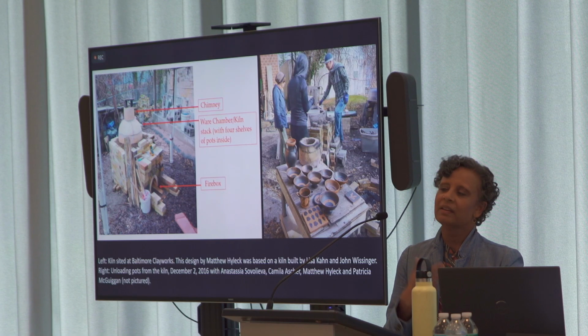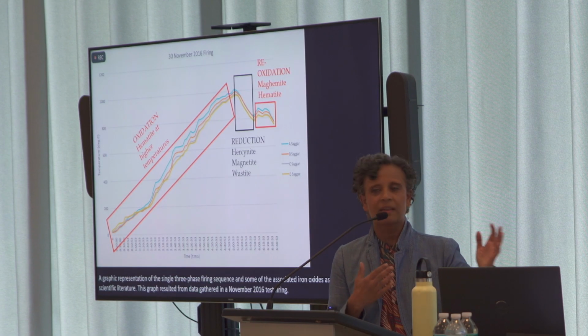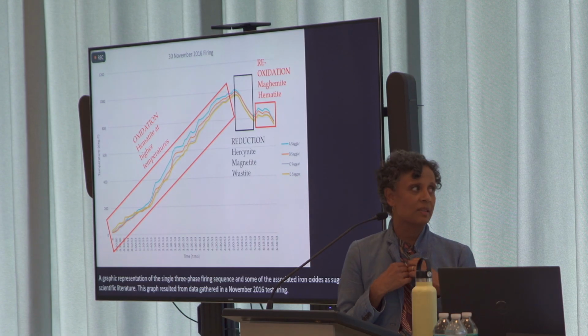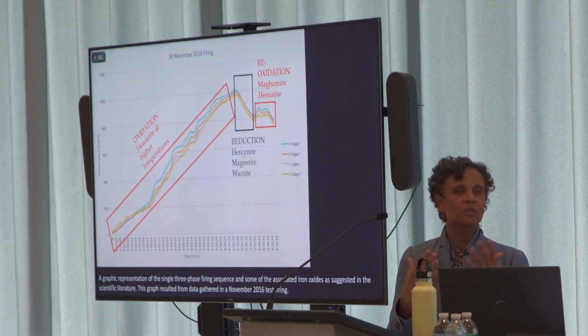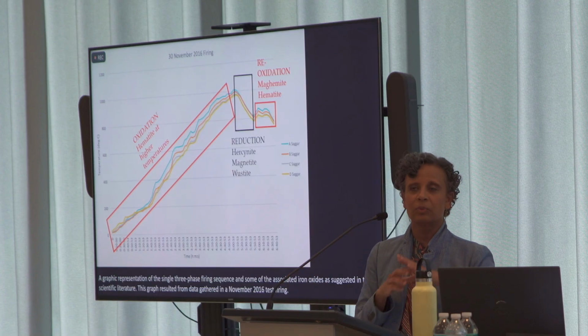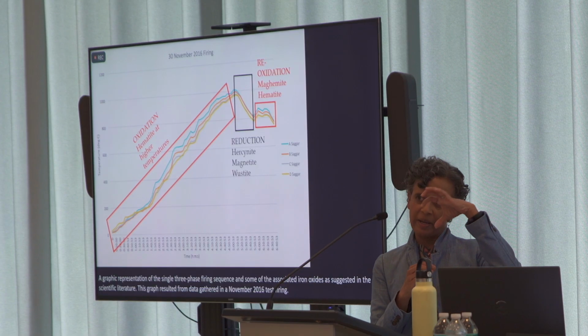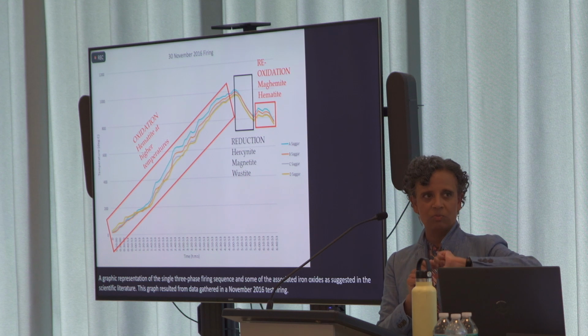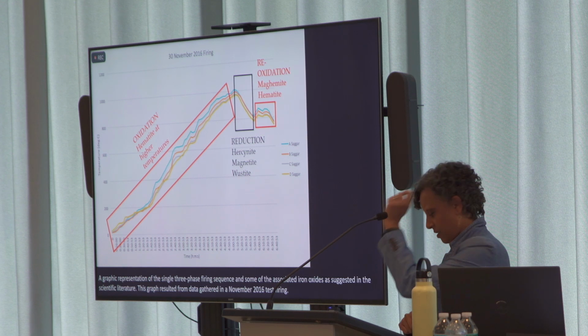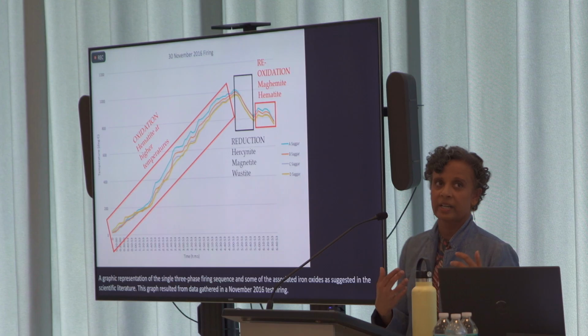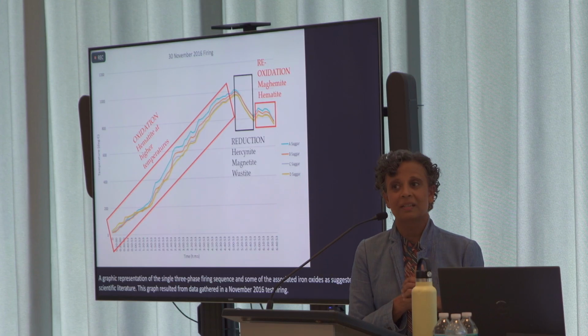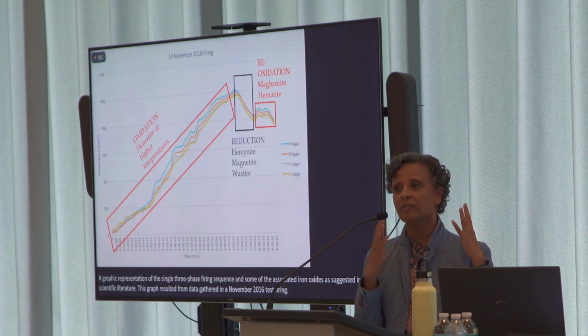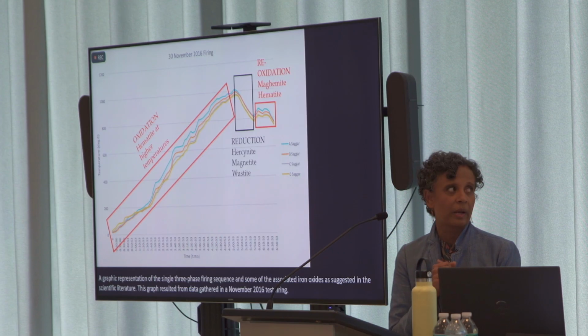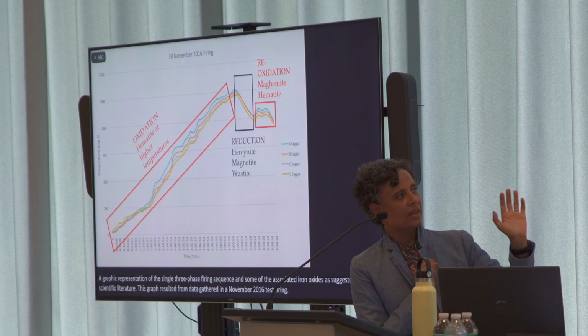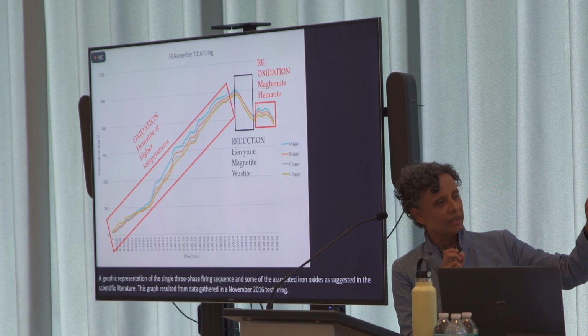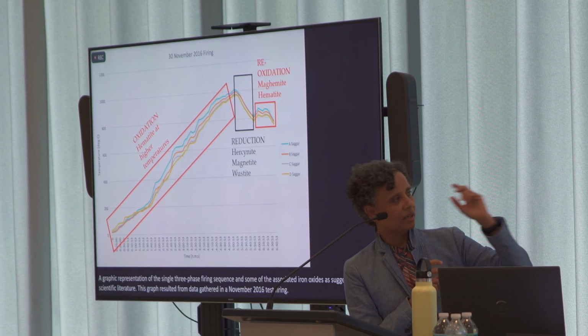So here's another way of looking at that production process that we can confirm from experiments that we ran. When things are inside a kiln, you can't see what's going on inside. We have some pictures from antiquity that show little spy holes where you could have reached in with a long rod, pulled something out and thrown it on the ground to see what color you were creating. But for the most part, you don't know what's happening inside the kiln. So you have to rely on other things that give you clues that you're doing the right thing. What you're seeing here is the analysis of one firing that we did in November